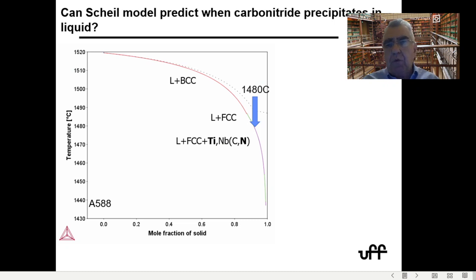So we can also use a one-dimensional or zero-dimensional model, which is just the Scheil model, in which you assume that the elements go into the liquid and partition and never partition back to the solid. It's a very classical way of describing solidification. This was devised back in 1948, I think. And then with the Scheil model, if we exaggerate the segregation, you can also see when these carbides or carbonitrides start to precipitate in the solidification.